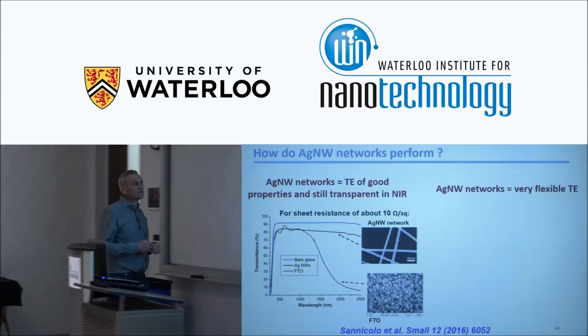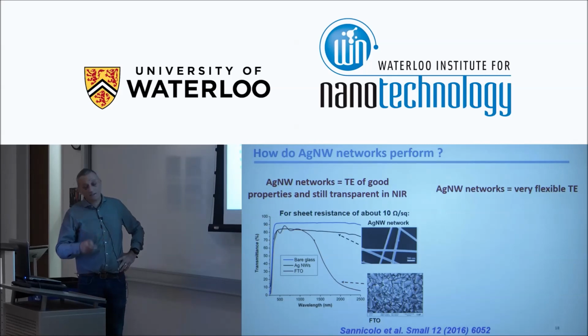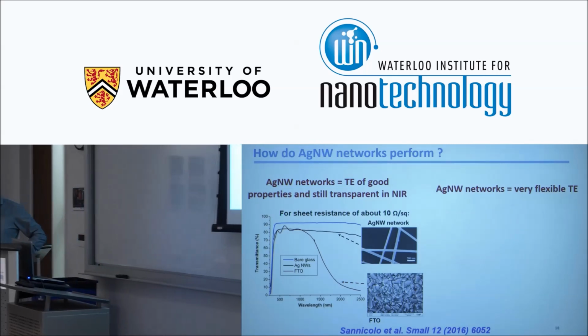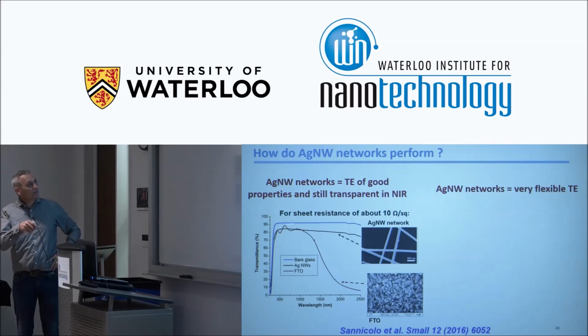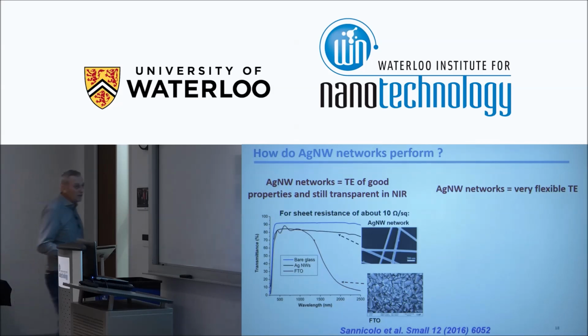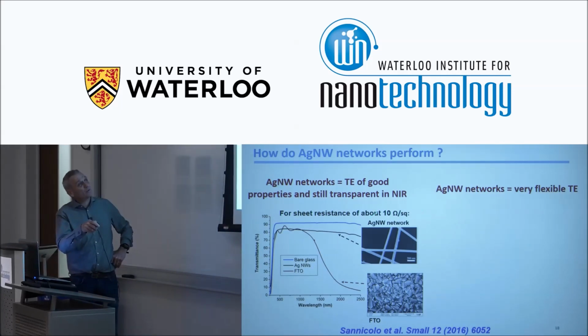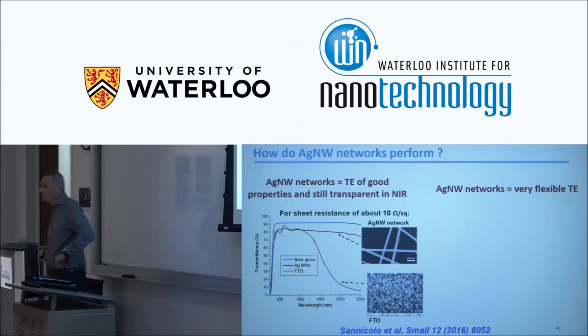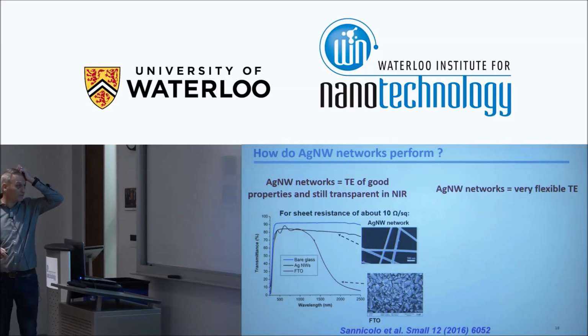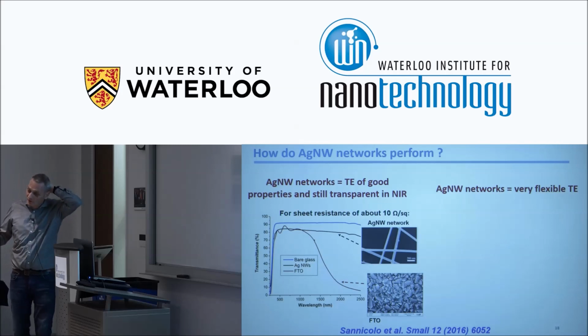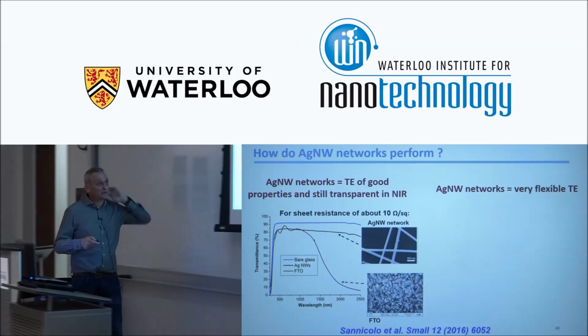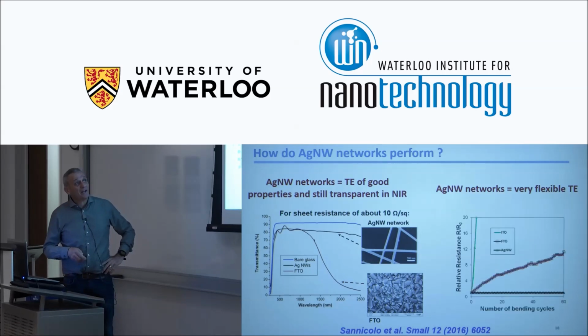The two main advantages of silver nanowire networks: the networks are still transparent in the near infrared. We can see that, the transparency versus the wavelength. You have transparency for bare glass, and this is the one from the silver nanowire networks. You can see the silver nanowires. There are some large gaps between silver nanowires, which give rise to the transparency. And even in near infrared, we are still very transparent. If you compare with a TCO, both sheet resistances were about 10 ohm per square, and transparency in the visible is about the same. But in the near infrared, there is some plasmonic absorption, which means that in near infrared, a TCO, a transparent electrode, is not transparent anymore. So if we target an application in near infrared, it's better to have silver nanowires instead of a TCO. And as well, it's very flexible.